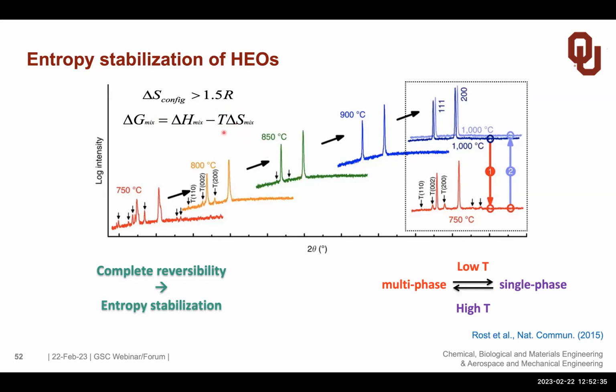And what you can do now, you go to high temperature, then this part dominates. And this is when you get a single phase. But if you go to lower temperature, of course, this T times delta S term gets smaller, and then eventually this term dominates. And then you have the complex enthalpic interactions of the atoms, and you get other phases. But you can go back and forth, and this proves actually in this system, it's an entropy stabilized configuration we have here.